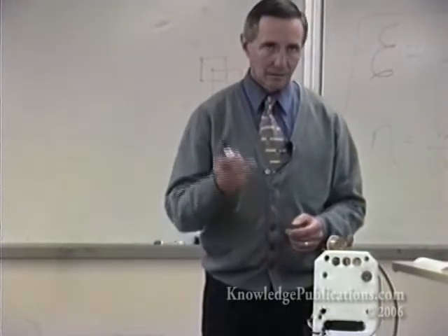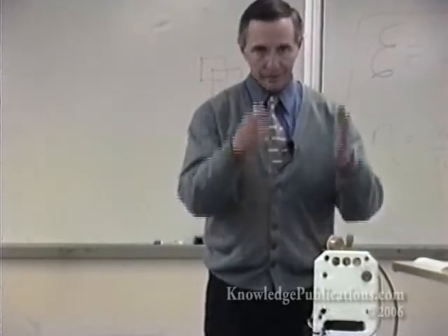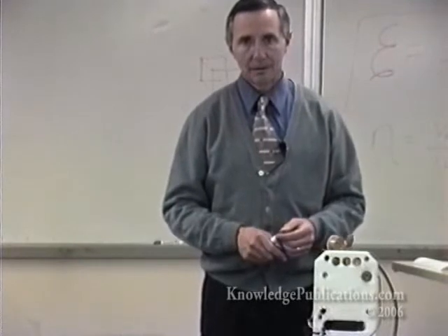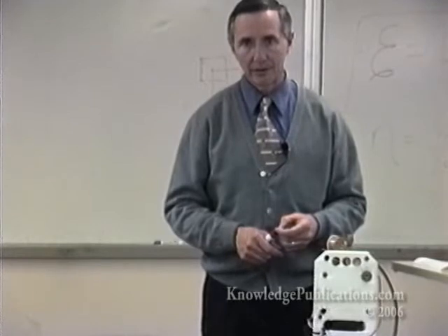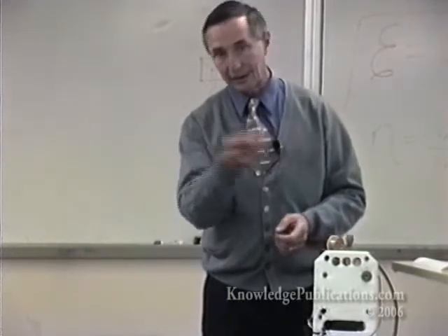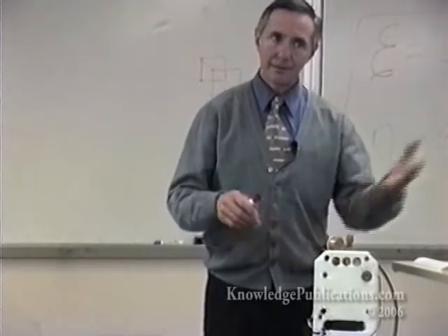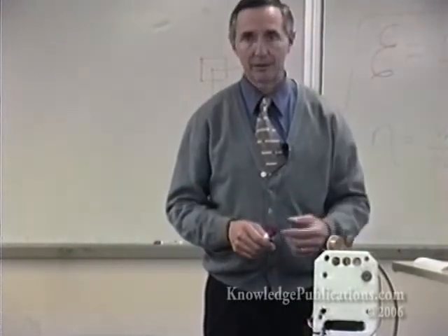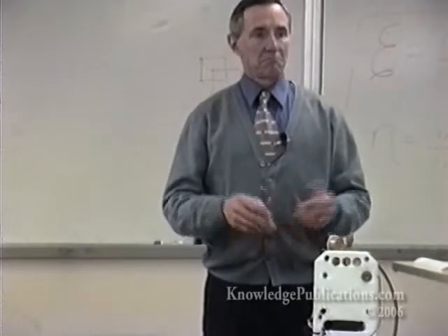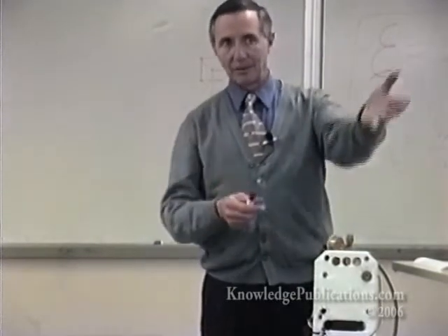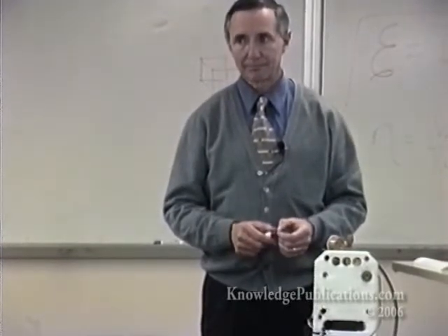You can run steam into a 1,000 degree fuel cell, apply voltage, dissociate the steam into hydrogen and oxygen, diffuse the oxygen the opposite direction as it runs in the fuel cell, and have hydrogen in enrichment on the other electrode. As long as you've got the energy. Sure. Use some waste resource to make the steam. Absolutely.